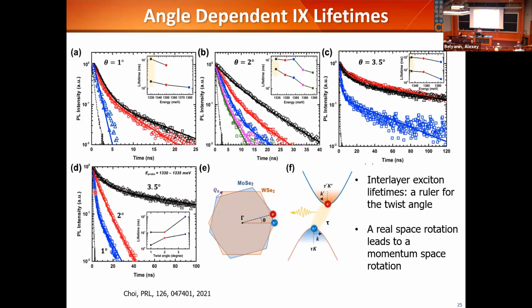This is the lifetime of the exciton. As you can see, the lifetime changes by more than an order of magnitude when I simply change the twist angle. Partially this is because of the same argument I've been saying, whether it's a direct transition in momentum space or an indirect transition in momentum space. When I twist these layers in real space, I'm actually shifting the bands in momentum space as well. So this picture would hold in momentum space. I'm shifting the top of the valence band from the bottom of the conduction band in this bilayer by a small amount, but that's sufficient to change the lifetime by a lot.